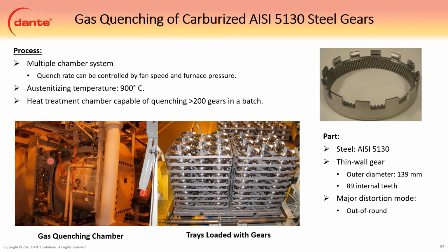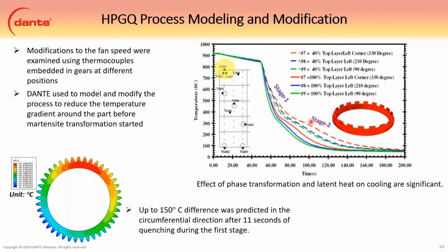So we looked at some ring gears, and of particular significance was the out of round distortion. So this thing was becoming egg shaped. You can't see it physically, but it's turning egg shaped. What they were doing was trying to manipulate the quench by manipulating the fan speed and the pressures, which essentially just affected the heat transfer coefficient. So Dante had no problem modeling this.